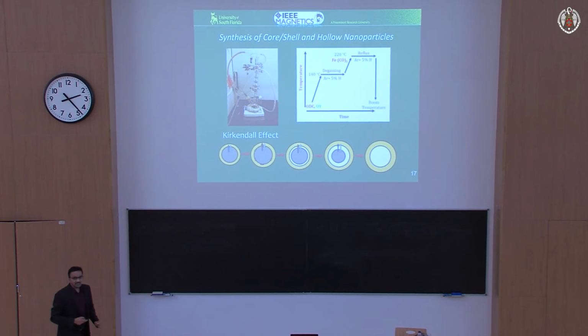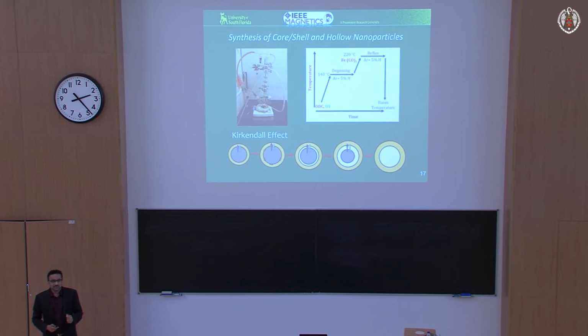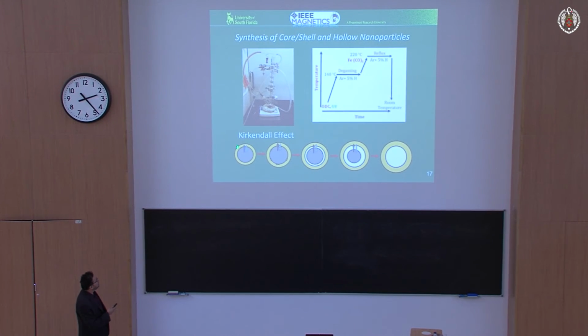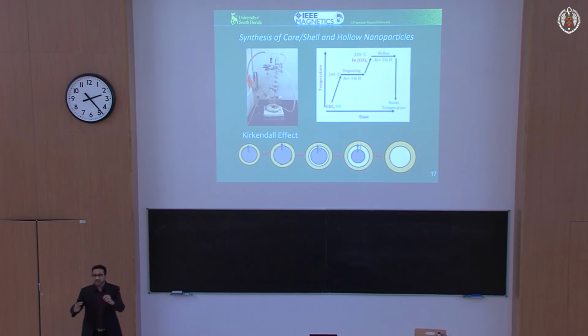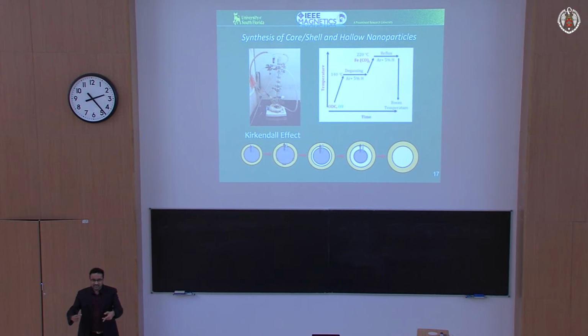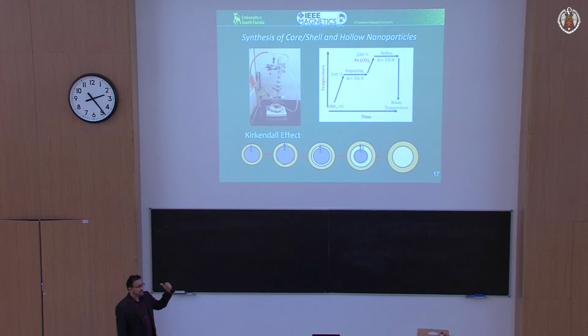Anyway, this Kirkendall effect is a problem because you start off with an iron core, iron oxide shell. Because of the differential diffusion of the metal ion in comparison with the oxygen ion, there is an instability at the interface, and because of that you have these voids opening up, holes. They become bigger and bigger. The iron in the core oxidizes and the shell becomes thicker. It becomes a hollow nanoparticle. So if you want to make hollow nanoparticles, start with the metal oxide core shell. That's what we found out.